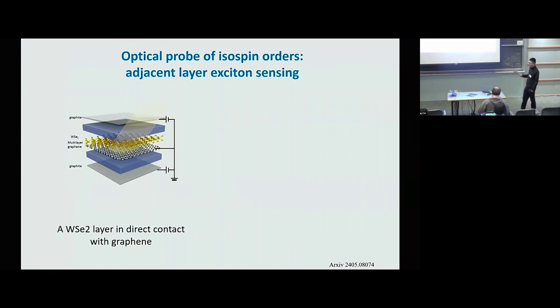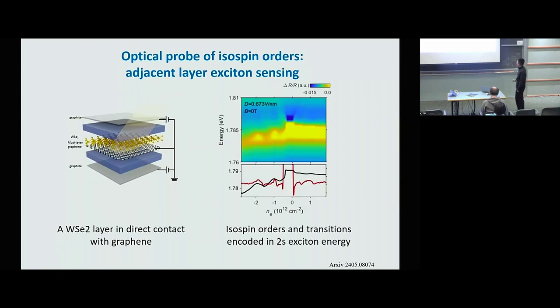So we know that these 2D semiconductors have a very strong excitonic response and a very strong light-matter interaction. So basically, we are effectively using this WSe2 layer, the excitons inside, as a sensor to sense the isospin orders in the adjacent layers. And we can call it adjacent layer exciton sensing. And I will not go into details, because that's not my focus today. So please refer to this arXiv paper for details. It discusses in detail what the principle is here and why it can work, so why we are able to sense isospin orders by looking at the optical response of the nearby WSe2 layer. Basically, if we believe this works, then we can simply measure absorption of the WSe2 layer using light, and that will tell us the information about isospin orders in graphene layers.